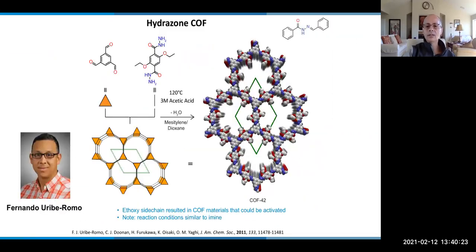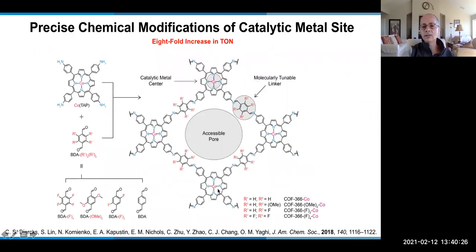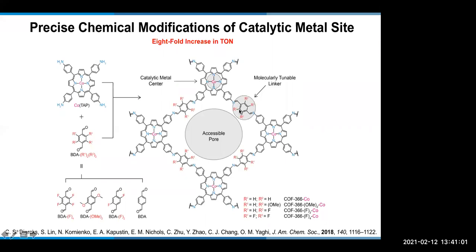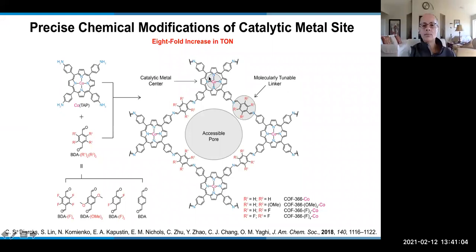But the other thing that I think is very interesting is that by functionalizing the linkers that are linking the catalyst sites, you're able to modulate how electron-rich or electron-deficient you want cobalt. In this case, we wanted cobalt to be more electron-rich so that you can have higher reactivity with CO2. And so you can functionalize without changing the backbone structure of the COF or its crystallinity. You can functionalize the linkers and modulate the electronic structure of the cobalt and get an 8-fold increase in turnover numbers.